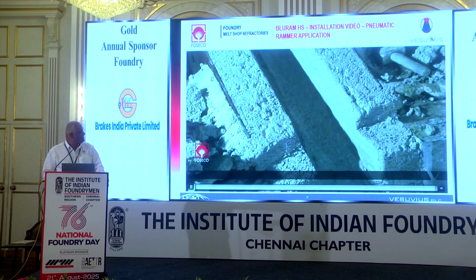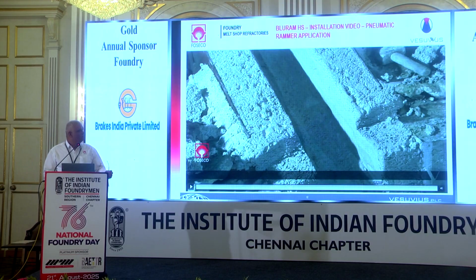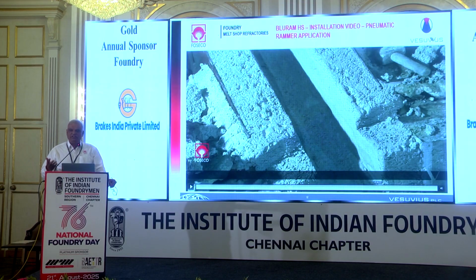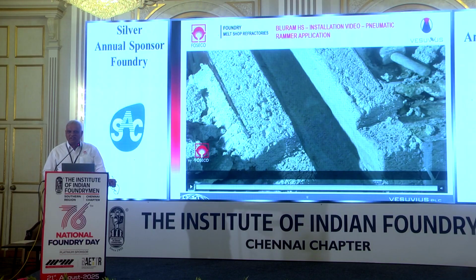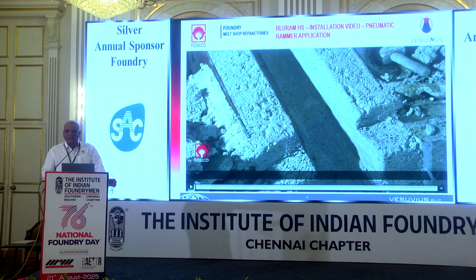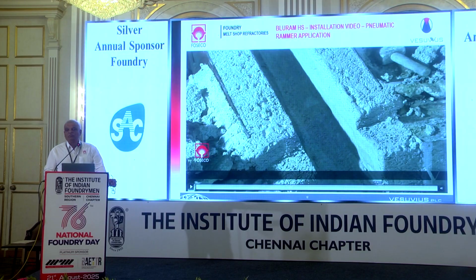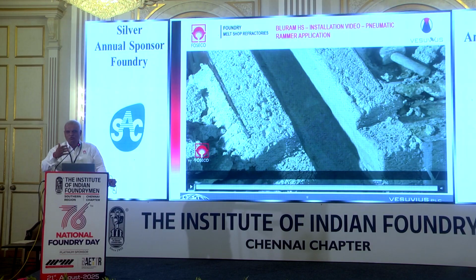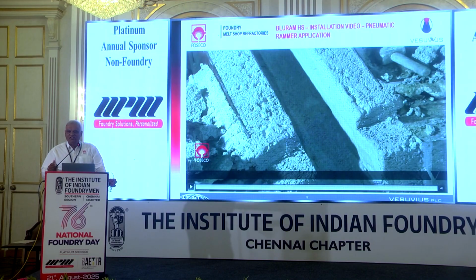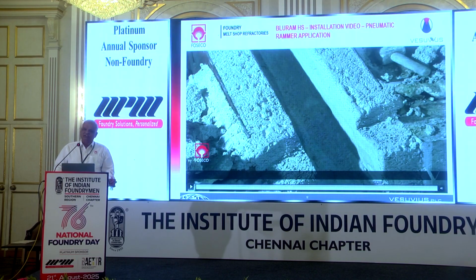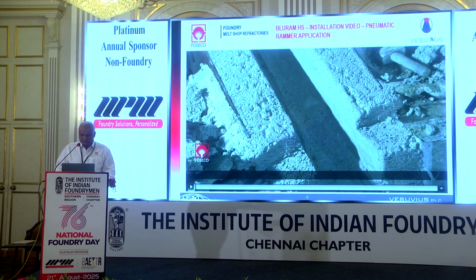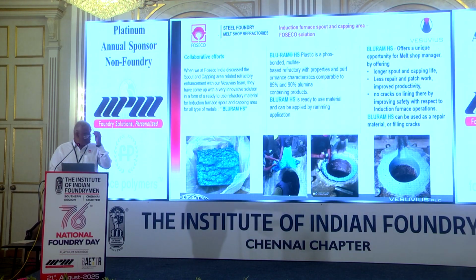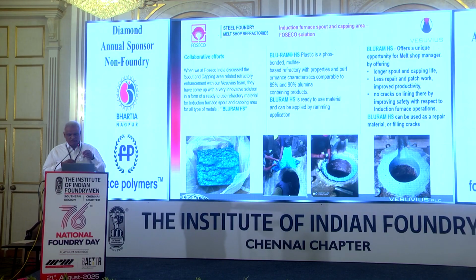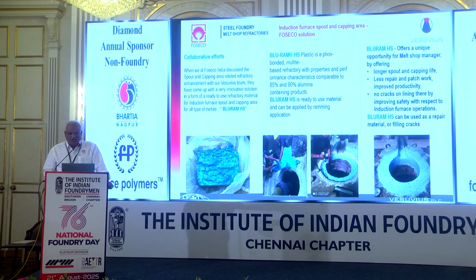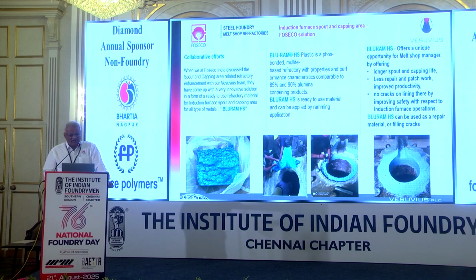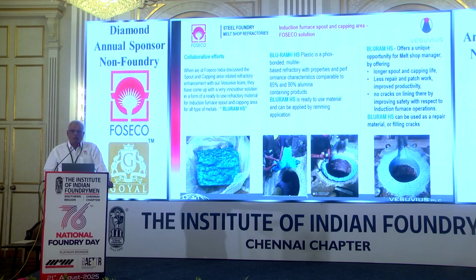You can smooth this material. So when you have to do lining, first of all you can make the spout and then start the lining. It is compatible with your lining material also, so there will not be any gap between the spout done first and the lining. So there is no chance of any metal penetration. So it has longer life. So what are the benefits we get from this material? Longer life for the spout, capping life increased, less repair required.